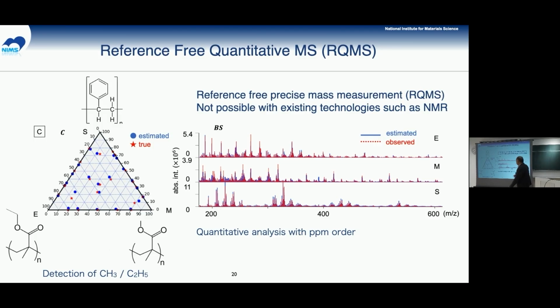So that is quite difficult, even with high resolution NMR spectroscopy. So as a result, that is estimated from the observed data. You can see contamination at less than 100 ppm order, so we can tell how much of these polymers is contained. That means you get polypropylene. Oh no, polystyrene. If a 100 ppm order of contaminant is included in the polystyrene, you can tell. So that is very accurate. That is quite difficult by NMR; you cannot detect such a small amount of contamination.